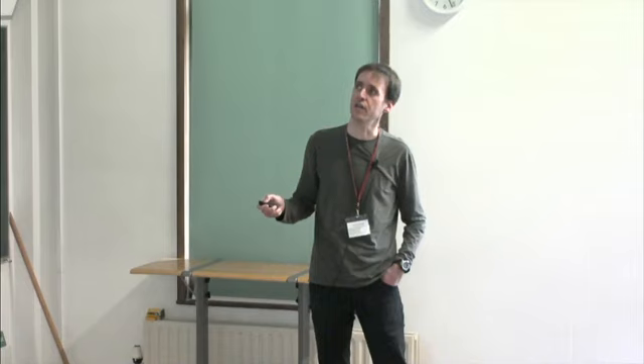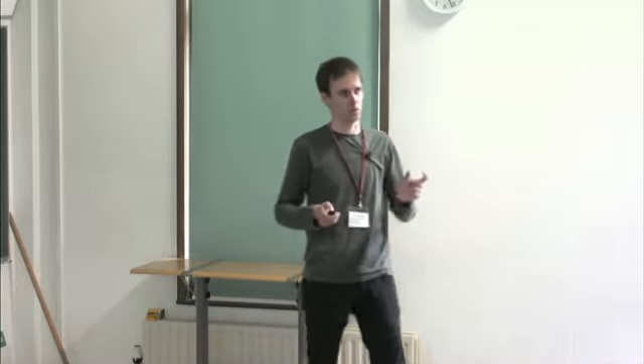If you look at the position of the two peaks, from the center to here is 3 units, and from the center to the first peak in the vertical direction is just 1 unit, and this is compatible with our 3:1 size ratio of our particles.